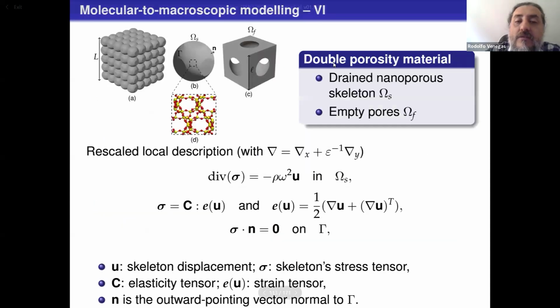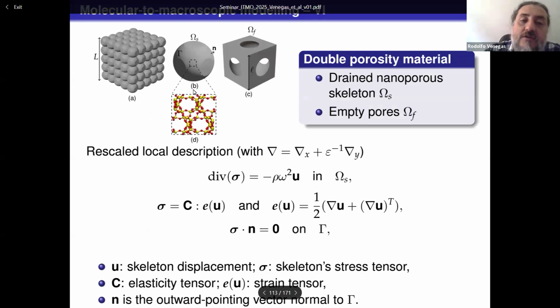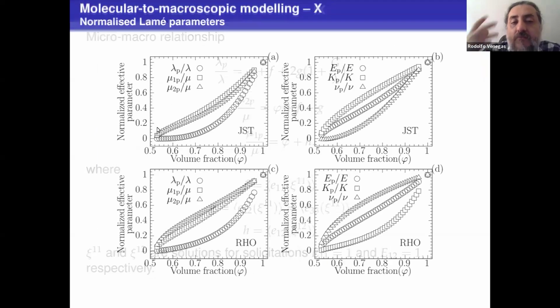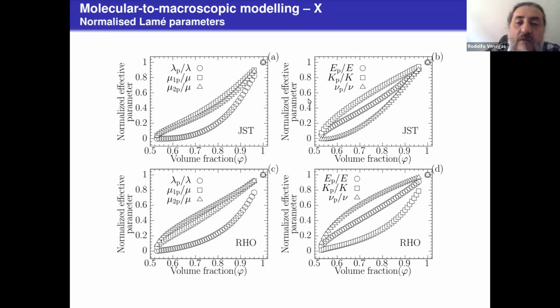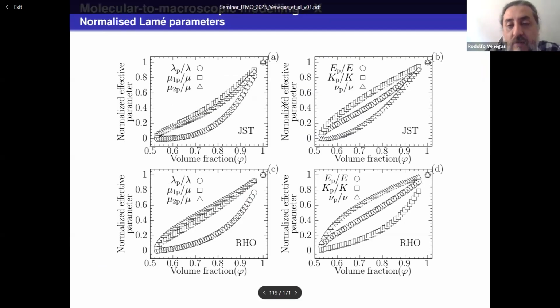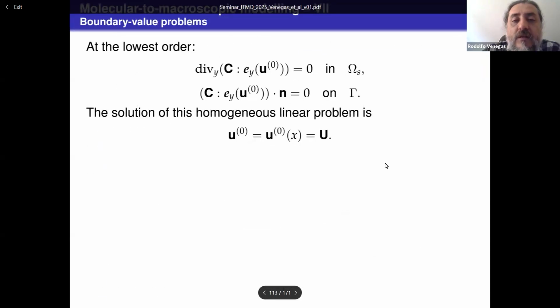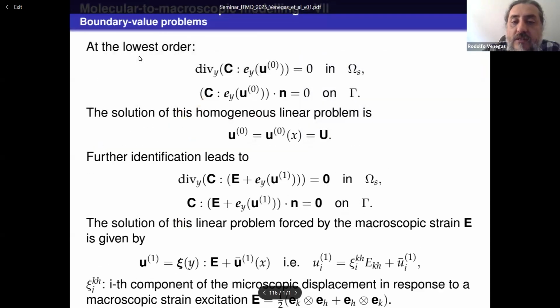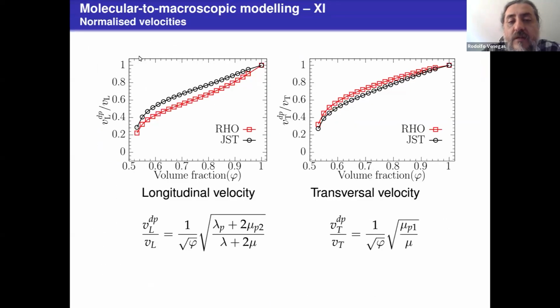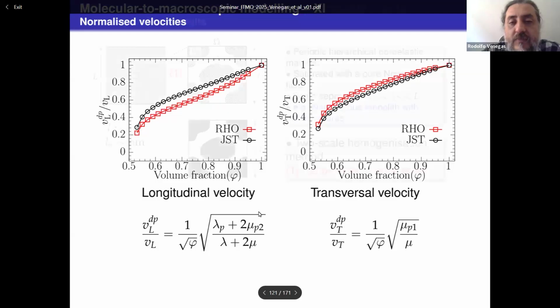So we use that, and then we use this as input to a model based on homogenization for a double porosity poroelastic material. So we have carried out the homogenization, and then we use these molecular dynamics parameters as inputs of this macro-scale model for double porosity poroelastic media to work out the, let's say, normalized Lamé parameters or Young's moduli, and see how the volume fraction of these consolidated grains changes the overall mechanical properties of the materials. And these are the normalized velocities.